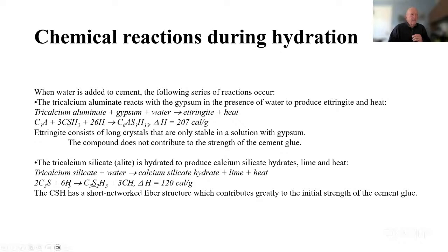But in addition to that, this tricalcium silicate is also going to generate even more calcium hydroxide. Okay. And it turns out that this base, this calcium hydroxide base, is one of the things that's catalyzing the polymerization of this calcium silicate material. Okay, and it's that polymerization that creates the glue that holds all of this concrete together. Okay. And notice also the amount of heat released. So roughly speaking, it's half of what's released with this tricalcium aluminate. Okay, so this second reaction is going to proceed soon after this ettringite is created.